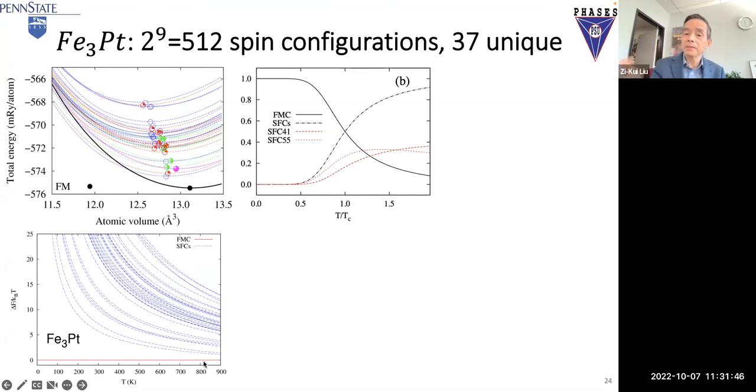From the classical thermodynamic point of view, the ground state should always be stable and nothing else should happen. However, from the statistical thermodynamics point of view, the ground state population will decrease. We decided that if the ground state becomes less than 50%, then when you sample the system you will not see that state anymore. You will see a mixture of everything. That's where we decided the system changed from ferromagnetic to paramagnetic. Even though the overall spin is zero, it still has local spins.